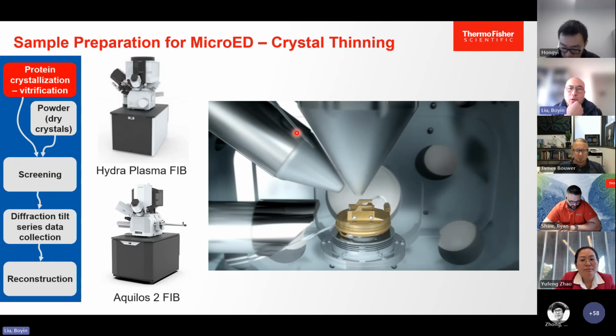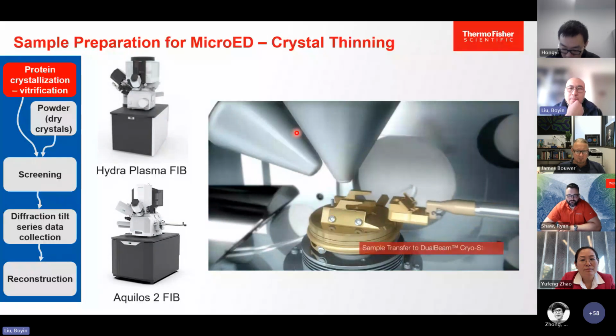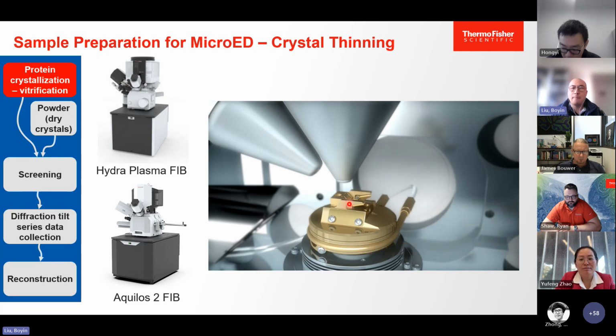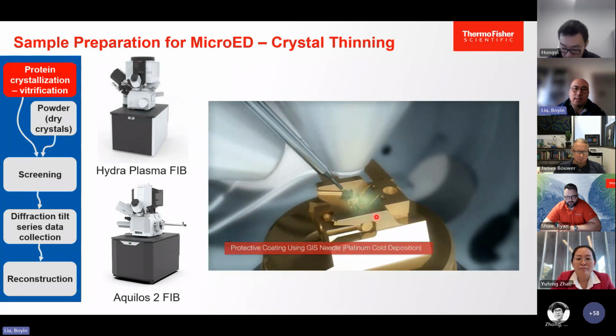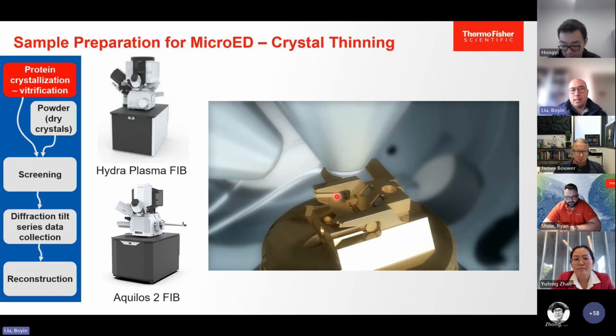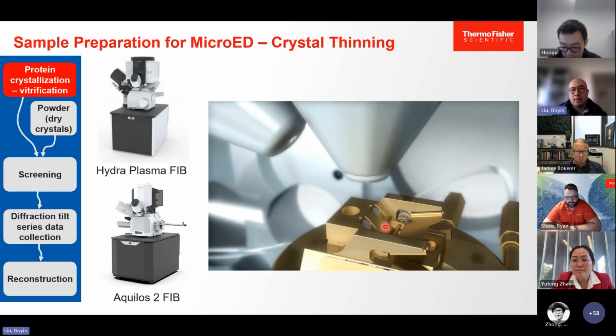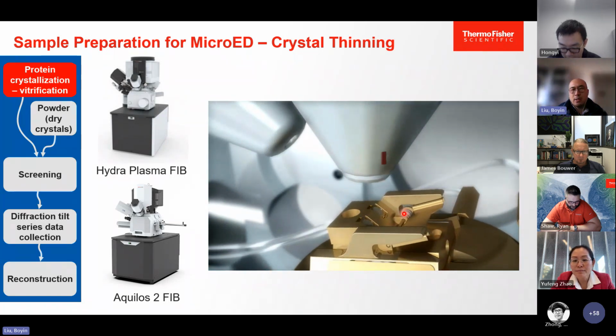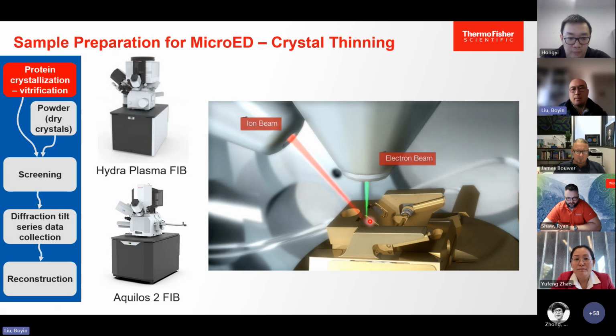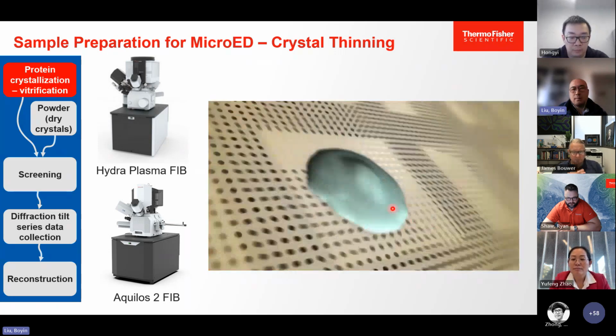So this is how it works. What you are looking at now is the FIB-SEM chamber. You have the SEM column, the ion column, and the sample can be transferred through the quick loader onto the cryo stage. Firstly, you can coat your sample with a protective GIS layer to protect it from ion beam damage, and then find the coincidence point for both electron beam and ion beam, so that they look at the same structure, the same location, at the same time.